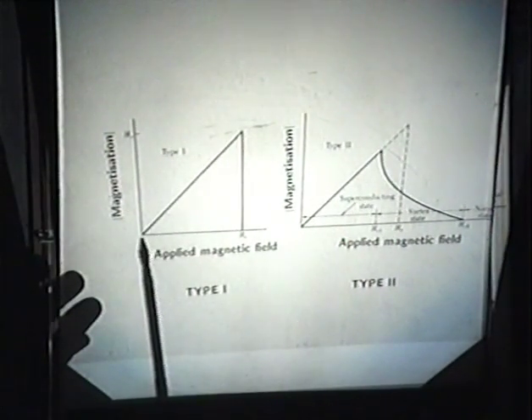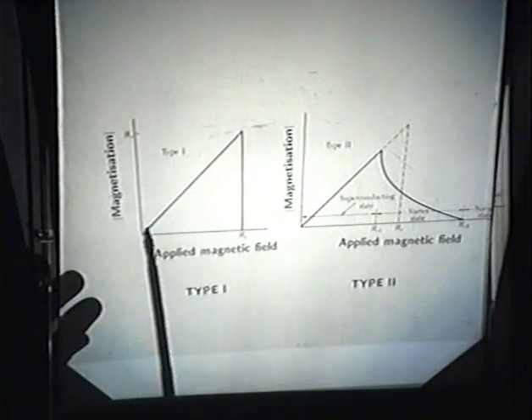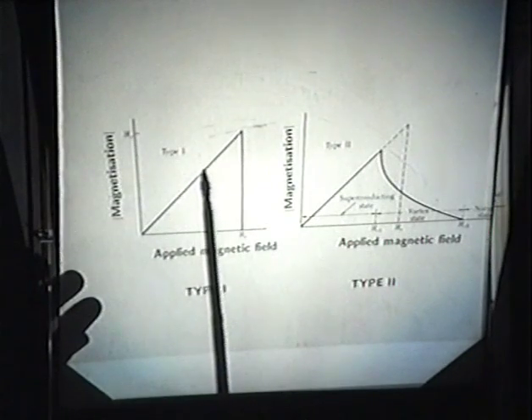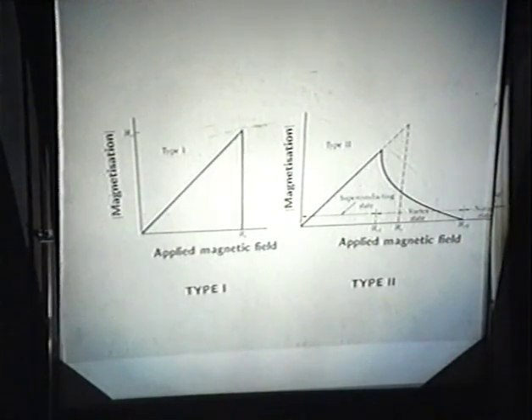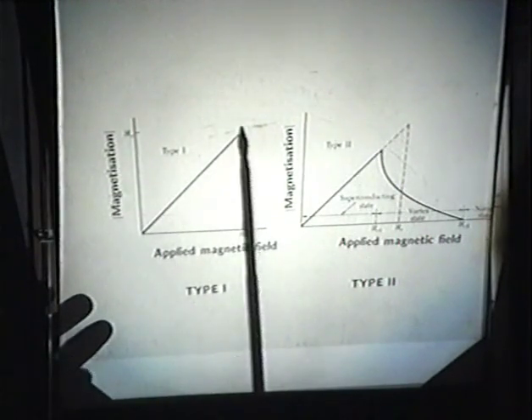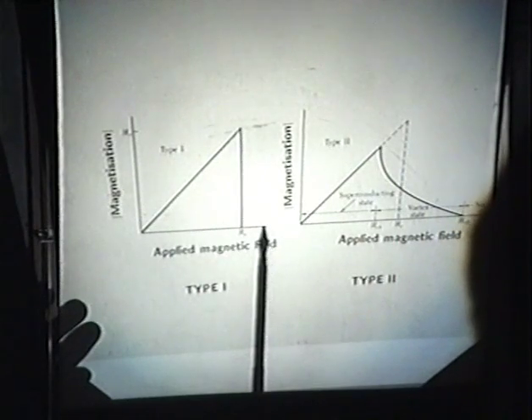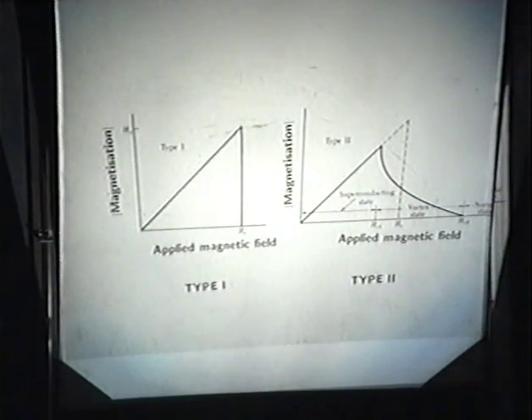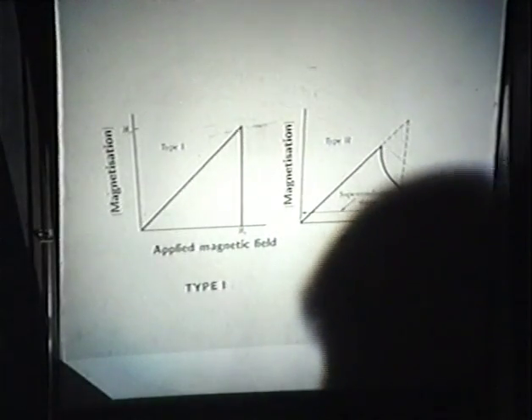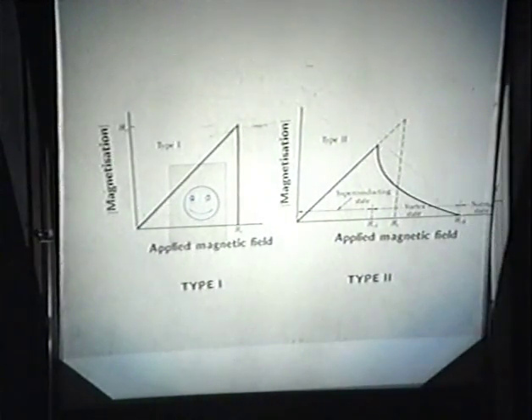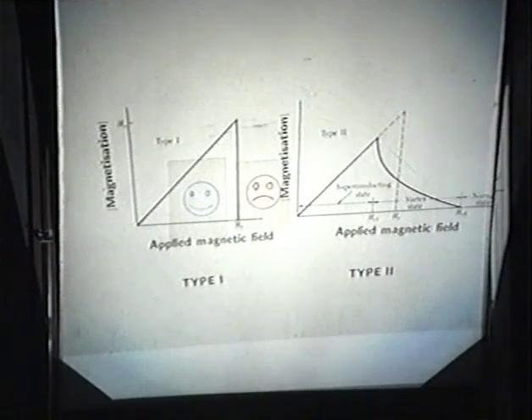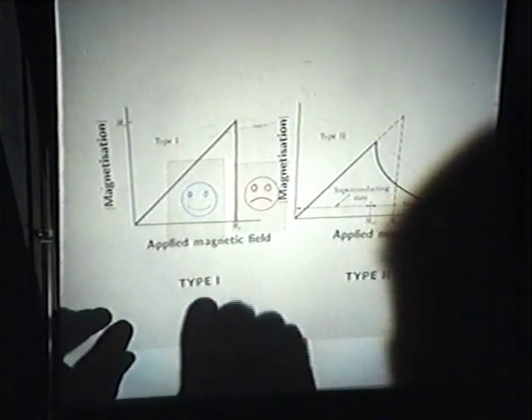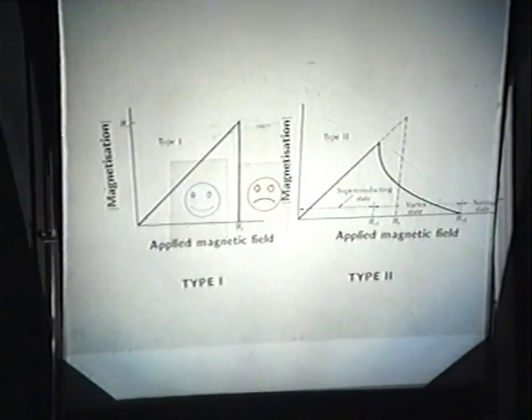So you can see that as you increase the external field, the superconductor responds by cancelling it out, and it continues to do so until it can't do it anymore, until it's no longer got any capacity for cancelling out the external field, and bang, it drops down and becomes normal again. So once again, down here in the low field situation, we've got the superconducting state again, and then once you've raised the field above the critical field, the superconductor can't keep the field out anymore, and it goes normal. The resistance returns. Cooper pairs break up. And that's the situation for just about all of the pure metal superconductors.